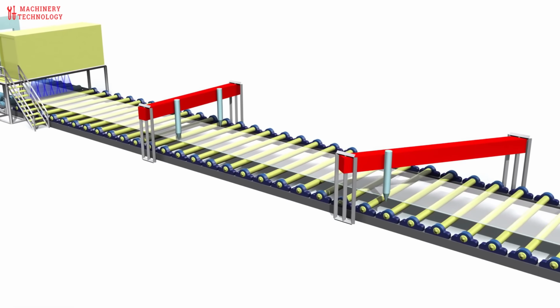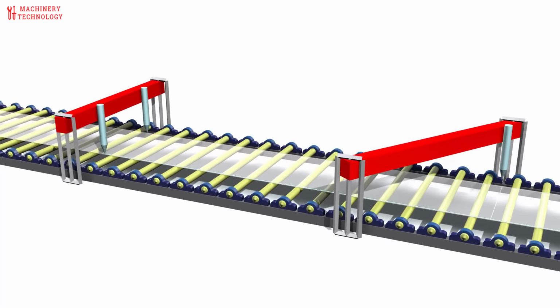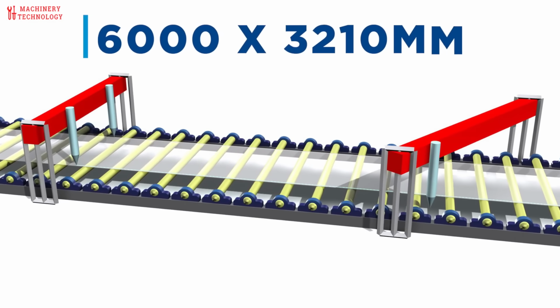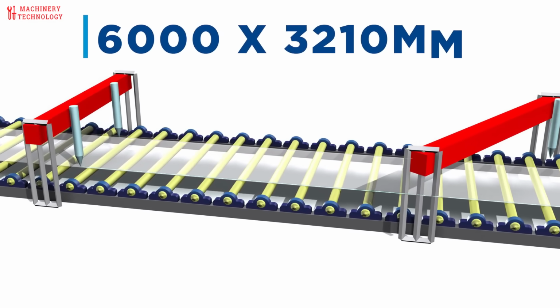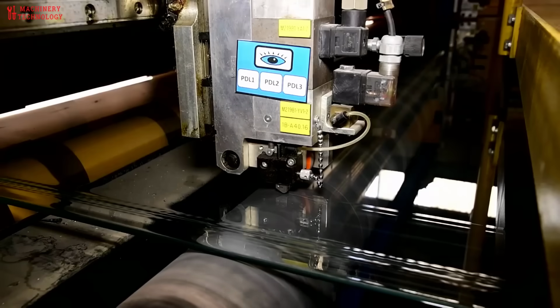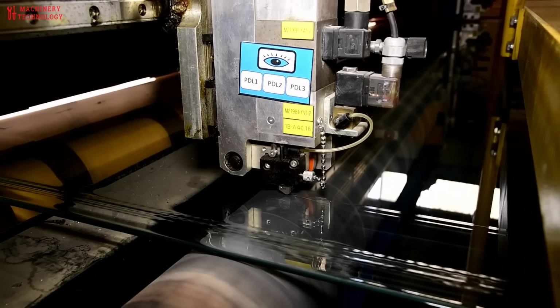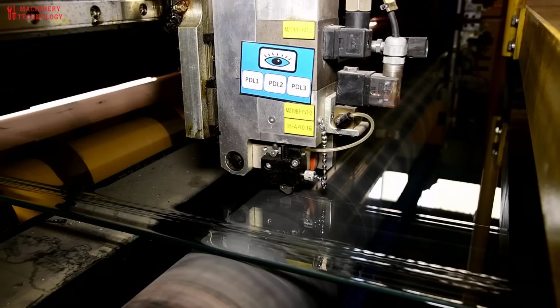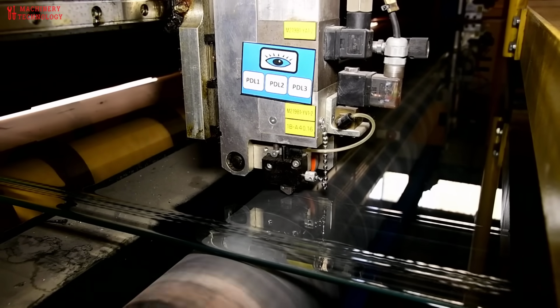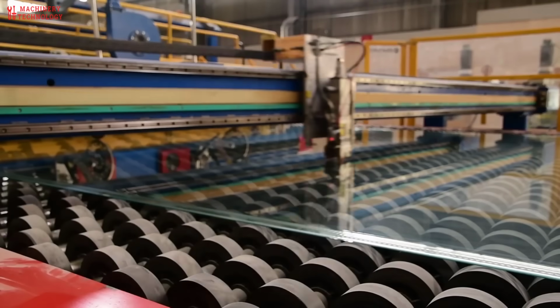Glass sheets are automatically created by a two-step cutting process in which the ribbon is scored and snapped along those scores to standard dimensions. The longitudinal scores are made by a diamond wheel that creates surface defects on the glass. This prepares the ribbon for the subsequent cut of its edges, thereby removing the top roll marks and obtaining the net width. Then, the transversal scores will determine the length of the glass plates.